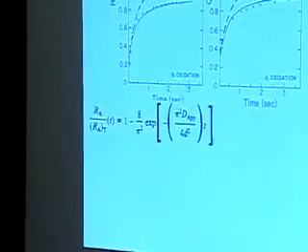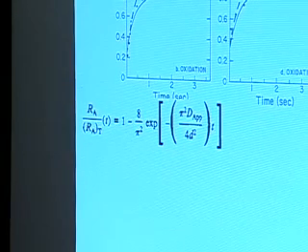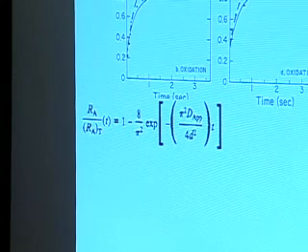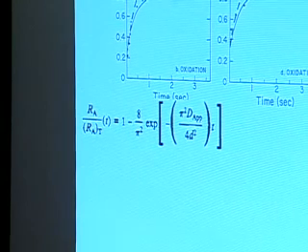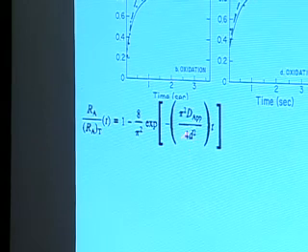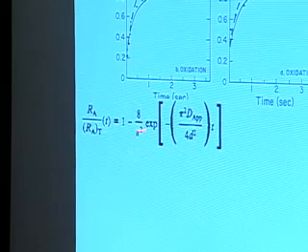But this is the equation. And you'll notice we switch over from a t to the 1/2 dependence to an exponential dependence. So pretty big difference. Here D is our normal diffusion coefficient, the little d down here is the thickness of the layer, and the pi's are in there, and everything else is sort of as you expect.